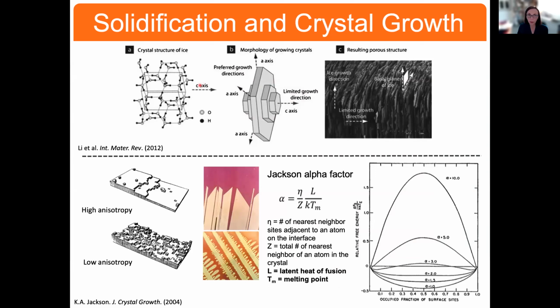Of course, the crystal structure of the solvent that one uses plays a role. If you look at the crystal structure of ice, as I've shown here, when that begins to freeze, you can see in this diagram that there are preferred growth directions. And if you were to use water to produce these porous ceramics, you'd end up with these structures that look as they do on the right here, where the solid material almost looks like a deck of cards. These are lamellar type structures. And the ice crystals that have now been sublimated would be between those layers.